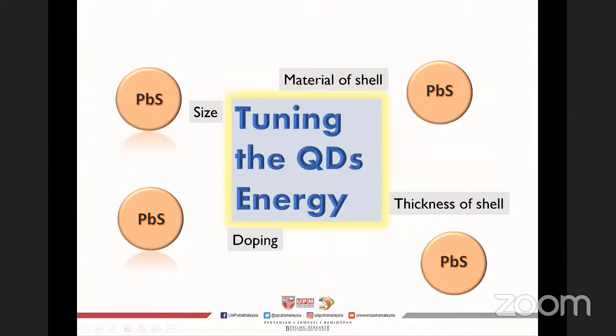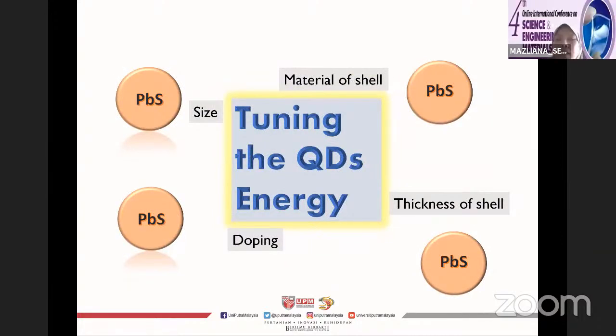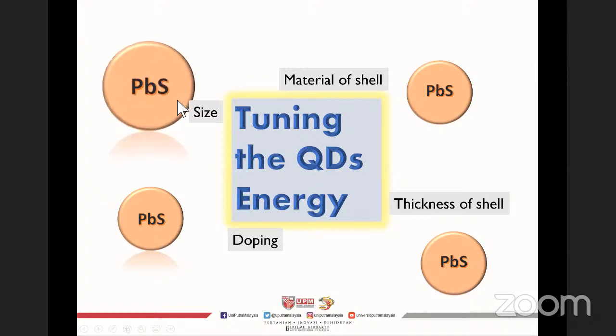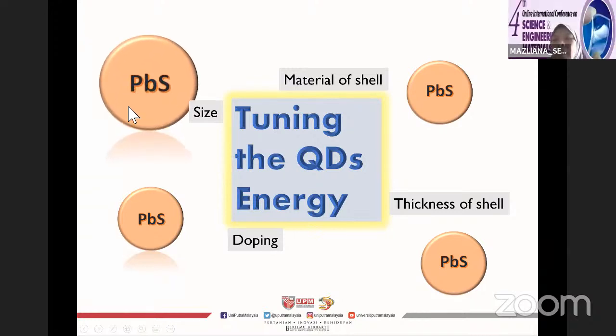So as I mentioned, in my study, I synthesized PbS quantum dots. That's why here I drew all the PbS quantum dots, and we try to tune the energy of the quantum dots. The first approach that we can use to adjust the emission is to adjust the size. So we can grow different sizes of quantum dots. And then we also can dope the quantum dots with metal, for example, manganese. That way we can have an excess of carriers in the samples.